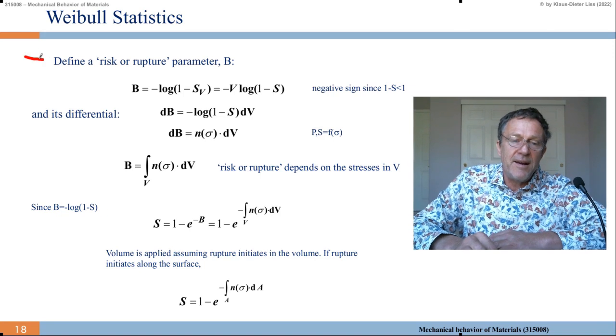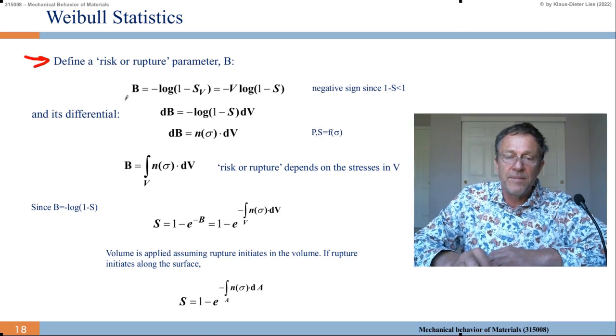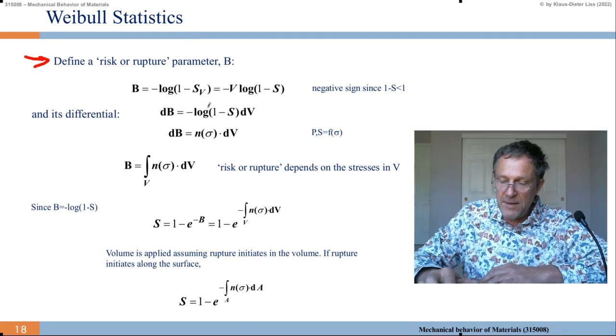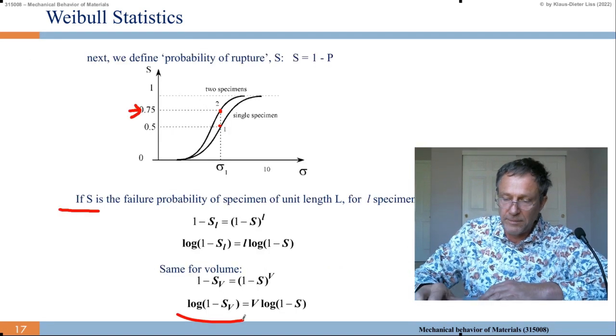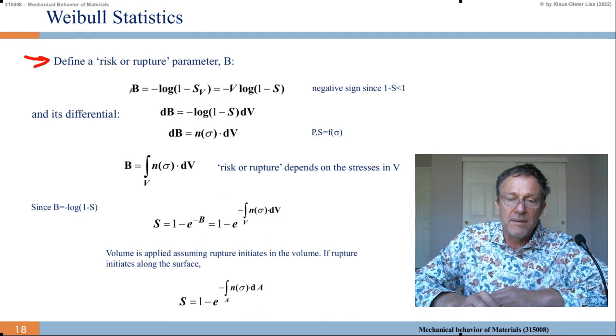So now let's define a risk of rupture parameter B. So this log of 1 minus S_V, which we introduced here, we call B. And this is minus V times log of 1 minus S. And it has a negative sign because 1 minus S is smaller than 1. And we can take the differential now. So dB equals minus log of 1 minus S dV, or dB equals, now we call this minus log of 1 minus S an n of sigma, times dV.